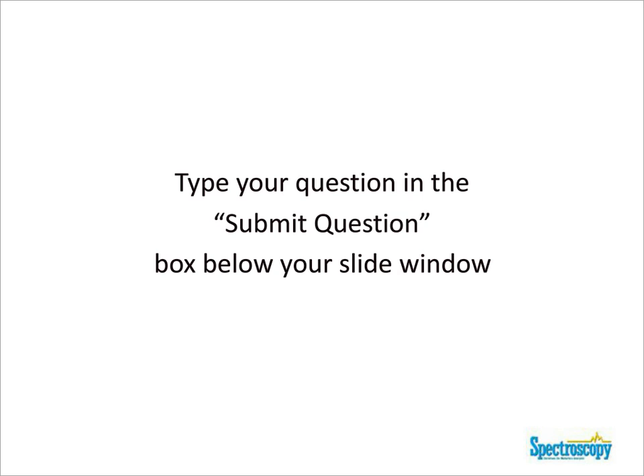Excellent. Kevin, I'm going back to you. What is your opinion on the use of UF techniques like Amicon filters to remove much of the dissolved fraction in order to reduce the background signal? I can't see how that would help, simply because with the Amicon, what you're interested in is getting the retentate, and in the retentate you'd have less and less dissolved. The columns that I was showing you, you can go directly online, so you're pumping your sample through the columns and looking at the particulate and retaining the dissolved. So it's sort of the opposite of what's being proposed there. Though I really encourage people to try all sorts of columns. There are probably lots of columns that we've missed.